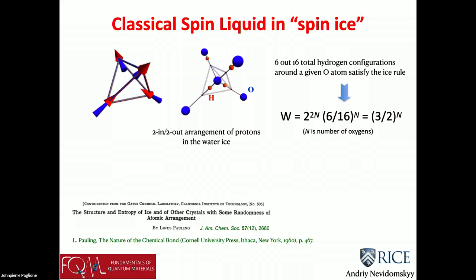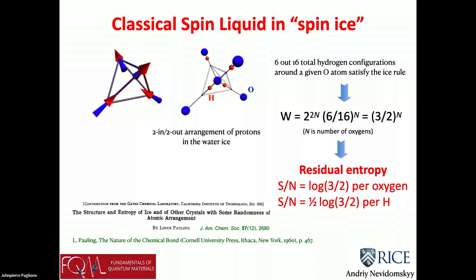And the reason is, if you look at how many configurations each of these hydrogens could have, farther in or farther out, that's 2 configurations. You have 4 such hydrogens, so a total of 16, just combinatorics. Out of the 16, only 6 satisfy the constraint that 2 of them have to be closer and 2 of them have to be farther apart. Or in the language of the arrows, 2 of them have to be pointed in and 2 of them have to be pointed out. And if you compute what this means, this ratio of 6/16 enters in the total number of states. If you take a log of that, you get a residual entropy, which becomes 1/2 log 3/2 per hydrogen.